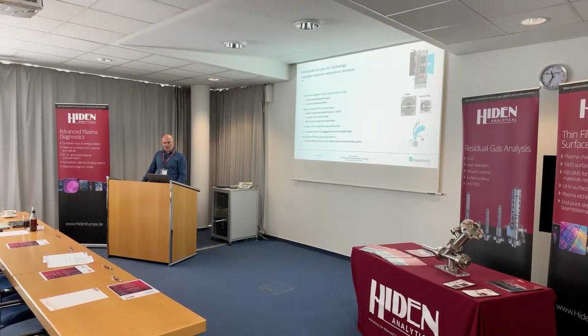What is also important, as you know, is that whenever you have arc coatings, you have the problem with droplets in the case of metal films or nitrides, oxides, and so on. In our case, there is no solid graphite droplet; these are particles, and so we have particles in our films. If we do filtering, since we have plasma anyway, we can use magnetic fields to bend the plasma, as you see in the right picture at the bottom. Then we can do plasma filtering and get smoother coatings.